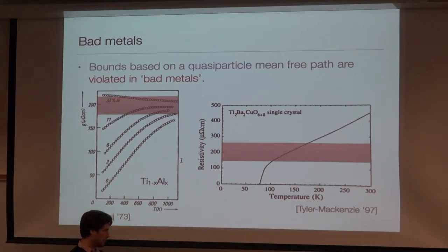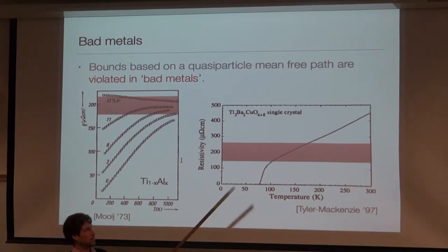So yeah, indeed, another logical possibility, I mean, these bounds are definitely not theorems, and maybe they just don't apply. That there are quasi-particles, but for some reason, the intuition that goes into these bounds doesn't apply in those materials. That's definitely possible. And then you can see that for a lot of metals, at least, the connection between, say, lattice spacing and Fermi de Broglie wavelength might be reasonable because, well, assuming that each atom contributes an electron, which, of course, is not going to be the case for bad metals. But yeah, I think so. Maybe just say one more thing, on what is a more positive statement, is that this bound, think of it as dimensional analysis, roughly gets the resistivity right of conventional metals. But for these bad metals, it doesn't really get the physics right.